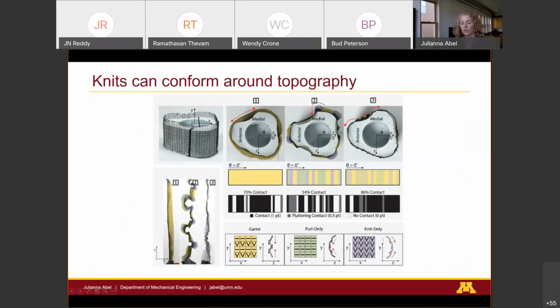And so we were able to use those structures I mentioned earlier, where we're getting these different bending motions in different directions, to create a functionally graded garment that would perfectly conform to the geometry of the leg. And so through that process, we went from low contact numbers up to very high contact of having 86% contact around the surface of the leg.